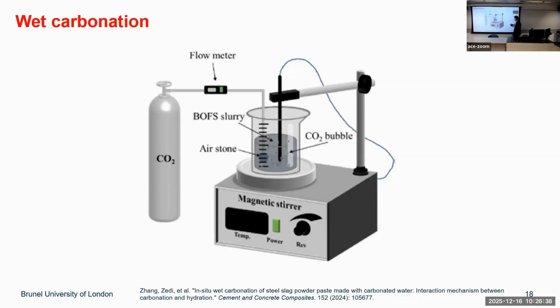We'll talk more later on about wet carbonation, or pressure carbonation. This is used very often in research, but later on we'll talk about the feasibility of scaling it up in industry. Generally, you have a carbon dioxide flow with a solution of cement particles, so you have a very high water-solid ratio, much more than the water-cement ratio needed.